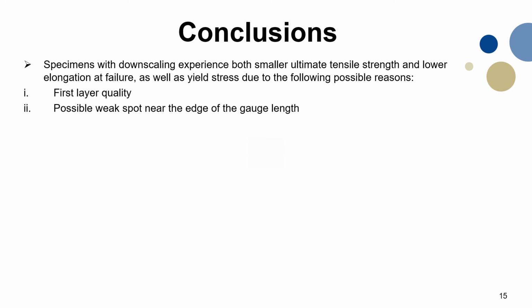Okay, so now we can make a conclusion. First, specimens with downscaling experience smaller ultimate tensile strength, lower elongation at failure, as well as lower yield stress, due to some possible reasons. First is the first layer quality. As you can see, especially for the FDM process, the quality of the first layer is very important, and it's affected by so many factors. That's why first layer quality has an influence on that.